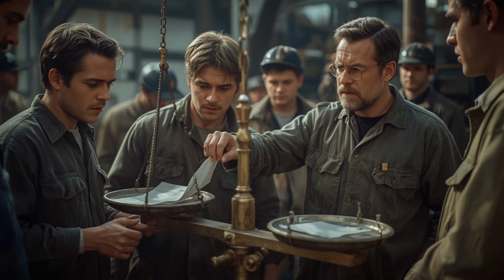Brass and iron both contracted when cooled. This was fundamental materials behavior. He calculated the thermal contraction. The 6-foot brass beam, cooling from 45 degrees to 28 degrees, would contract approximately 9/1000ths of an inch in length. Negligible. The knife edges would contract even less.